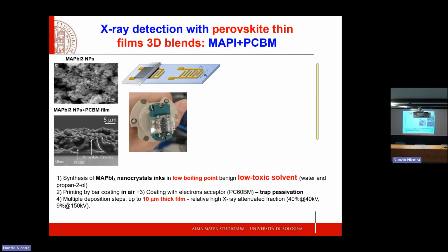Now, let me show you similar films based on perovskites. Look at the perovskite's very rough aspect. These are SEM images of MAPI, so methyl ammonium lead iodide perovskite. This is a pure MAPI thin film. The second image is MAPI blended with another polymer, PCBM, because we really understood that these blends are useful in passivating selectively the traps that we don't want.